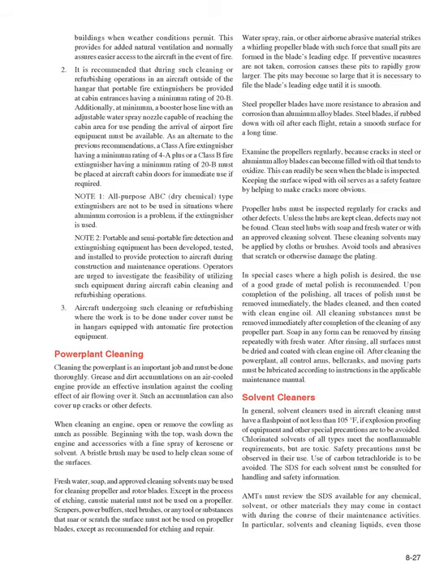Fresh water, soap, and approved cleaning solvents may be used for cleaning propeller and rotor blades. Except in the process of etching, caustic material must not be used on a propeller. Scrapers, power buffers, steel brushes, or any tool or substances that mar or scratch the surface must not be used on propeller blades, except as recommended for etching and repair. Water spray, rain, or other airborne abrasive material strikes a whirling propeller blade with such force that small pits are formed in the blade's leading edge. If preventive measures are not taken, corrosion causes these pits to rapidly grow larger. The pits may become so large that it is necessary to file the blade's leading edge until it is smooth.